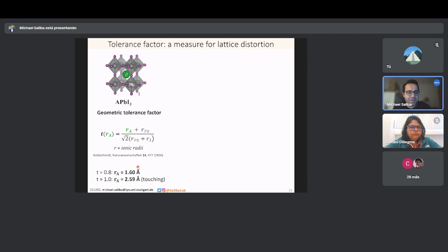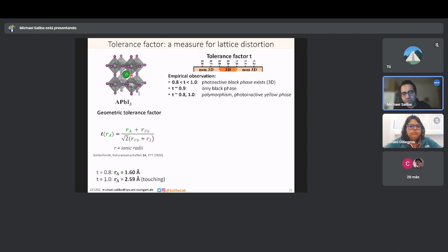So a tolerance factor between 0.8 and 1.0 leaves a gap for the cation. If we fix the lead and the iodine, because that's beneficial for the band gap, it leaves a gap of 1.6 up to 2.6 angstrom. Okay, and any component that has this kind of size fits into this cation position very well and stabilizes it there too. So schematically, it looks like this. Empirically, we know that that's the condition for photostability.